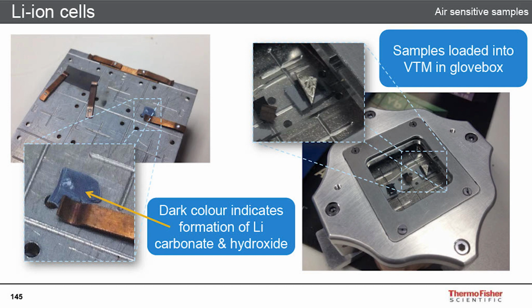And this is the same type of sample that we've just put into a little plastic bag and transported from the glove box at the Transport Research Lab through to the XPS system, which is in the main part of Oak Ridge. It was about a 30-minute drive, and we were able to keep the lithium metallic during that process, whereas the lithium metal we had just exposed to air goes this dark color with the formation of particularly lithium carbonate on the surface. So the vacuum transfer module is really useful for moving samples into the system from the glove box without exposing them to air, and that's what we need to be able to look at